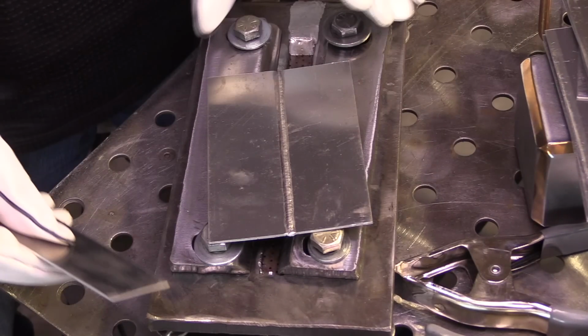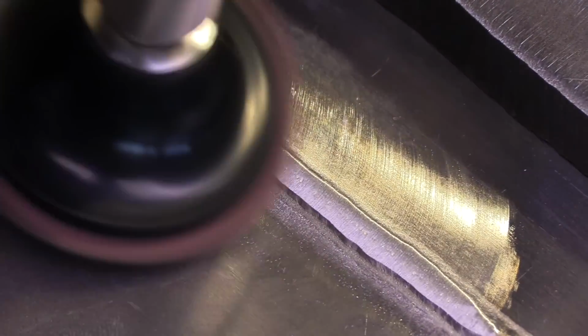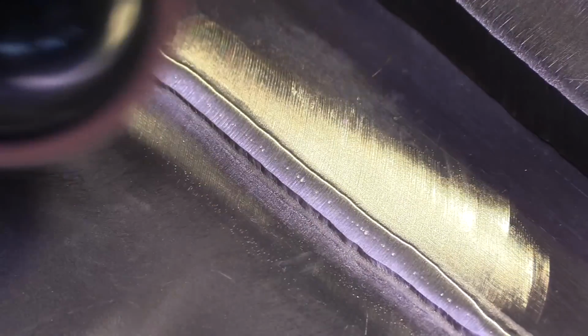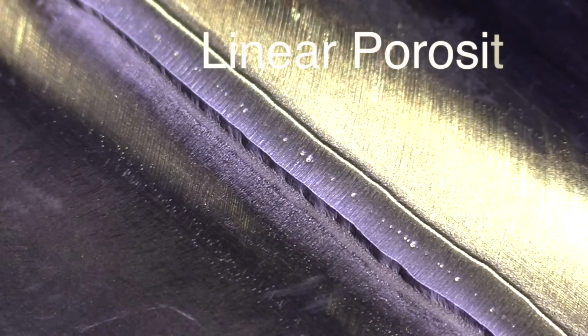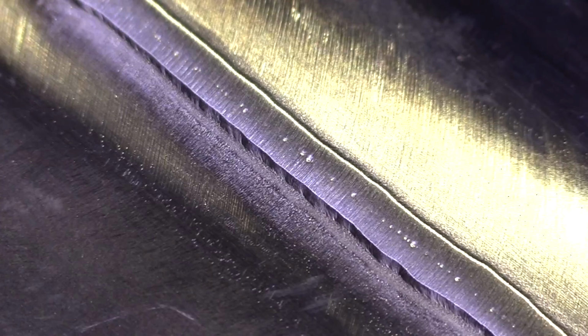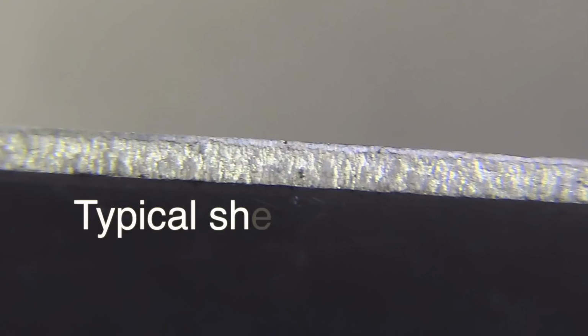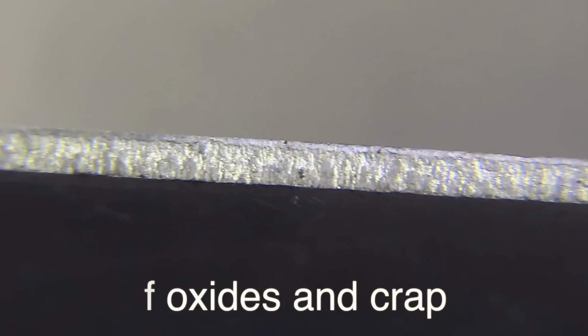Even on a full penetration weld like this, where the penetration side looks smooth and even, you could have problems. A quick polish will reveal those problems. Look at all that linear porosity shown with the polish on this weld. It looked good, but because this joint wasn't cleaned properly, there was way too much porosity for it to pass X-ray. A typical sheared edge looks something like this.